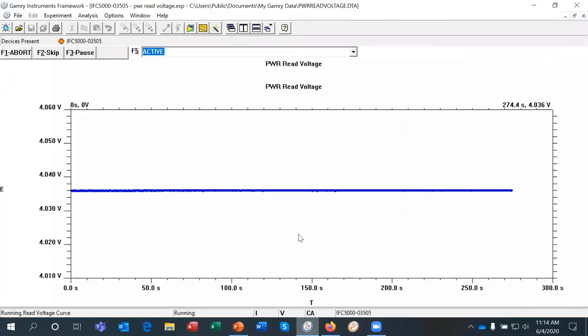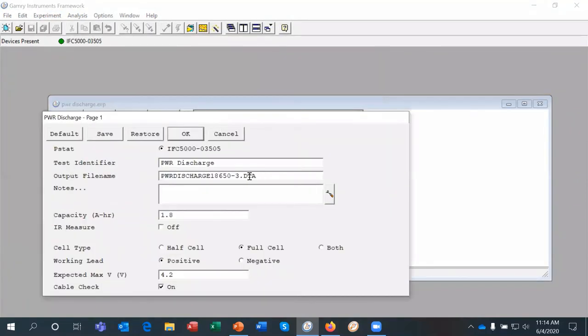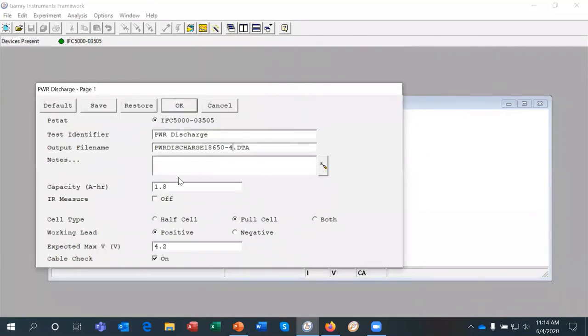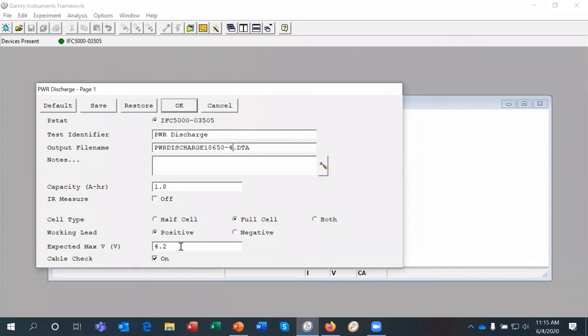So let me give you a quick demo of the demonstration of discharging the battery. So we'll run the discharge experiment. And again, we have a setup page very much like the previous one where we define a file name for the output file. We put in the battery's rated capacity. We can actually using a current interrupt method, we can measure that IR drop during the experiment, but I won't turn that on for this particular experiment. Again, we're going to choose that it's the full cell type because I have a battery that I'm testing. I'm going to connect the working lead of the potentiostat to the positive electrode. I expect the maximum voltage to be no, I don't want the maximum voltage to go greater than 4.2 volts. And I'm going to just, I know the connections are correct. So I'm going to uncheck the cable check this time.